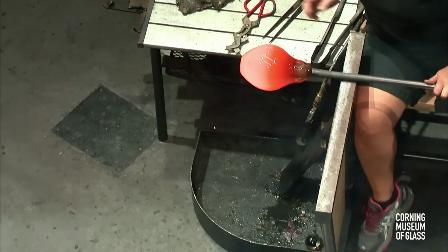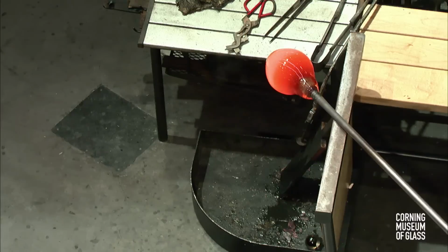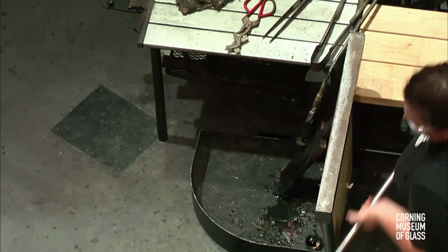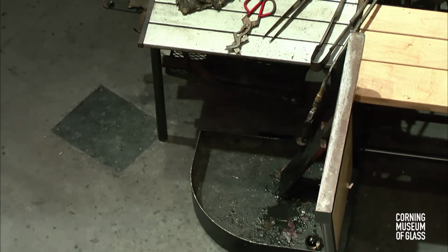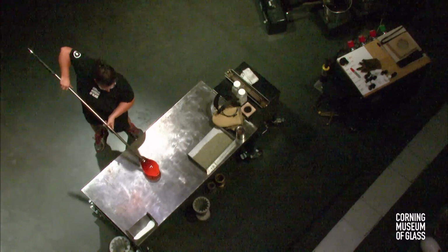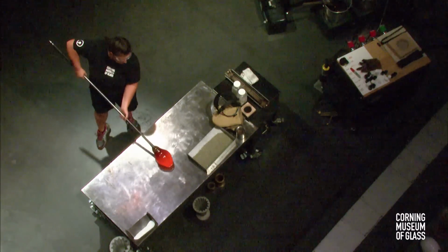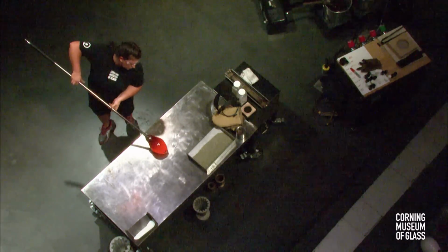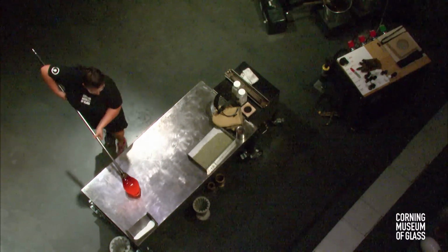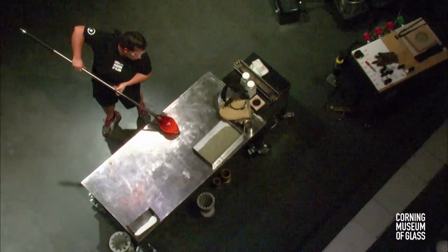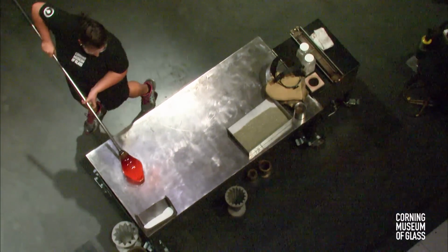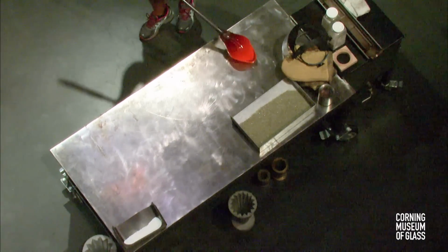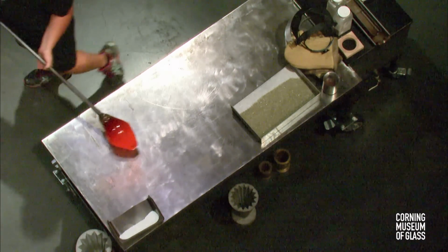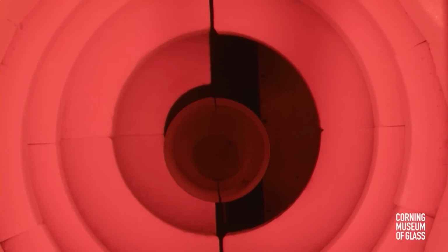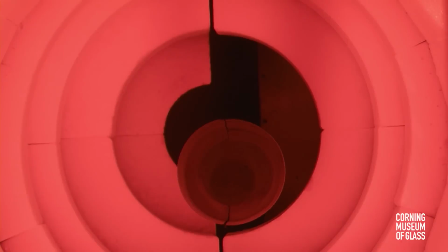I will always control the temperature up here. The hottest torch that you'll see Catherine use is a propane oxygen assisted torch. So that one gets about 4,000 degrees Fahrenheit. It does glow blue because of the intense heat behind it. And if Catherine left that intense torch on a single part, she could very well boil the color away, especially if it's on the outside surface of the bits of glass, because she will be using that torch, I believe, in order to sculpt our elephant heads down here. You can see we have beautiful tusks on the elephant. We also have eyes, so those will be flame worked or sculpted onto each elephant by hand.